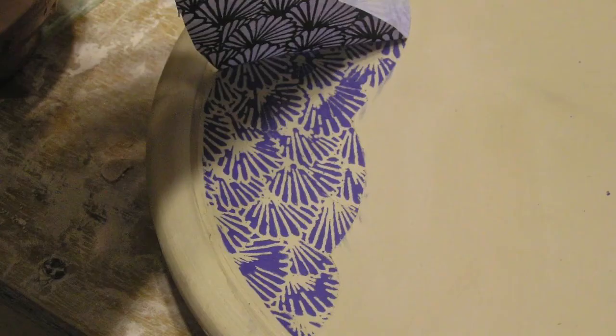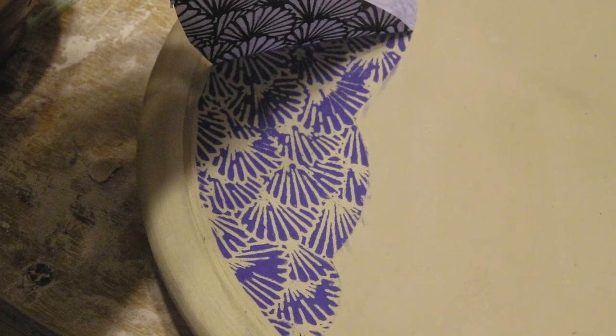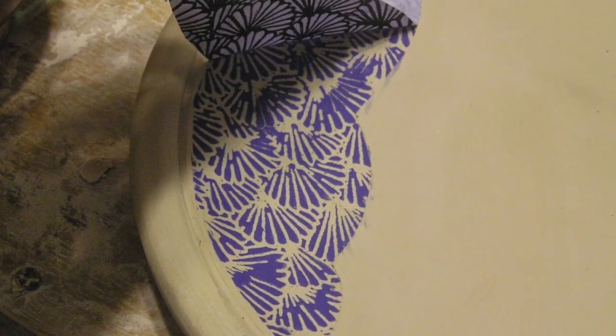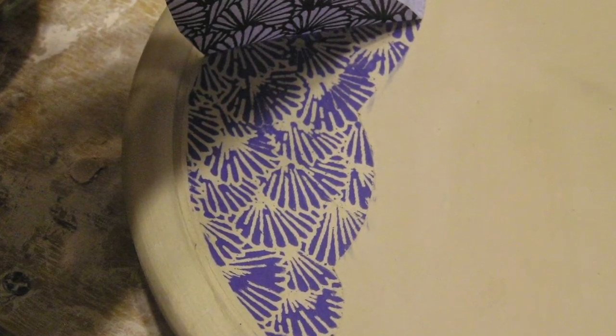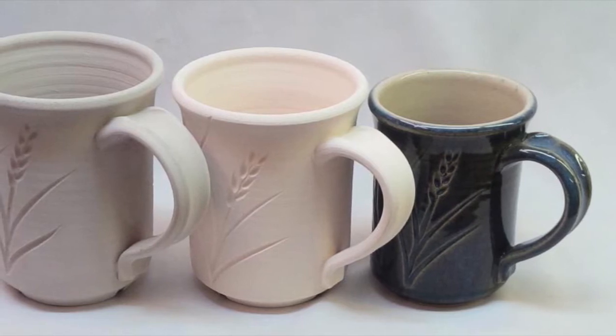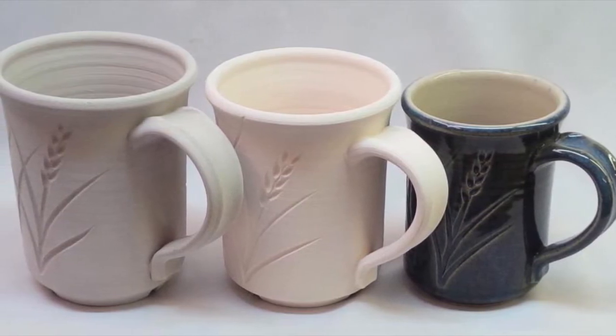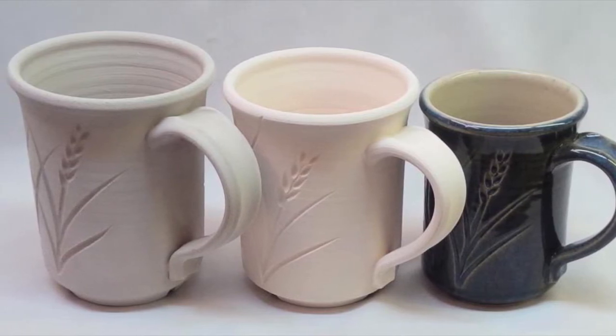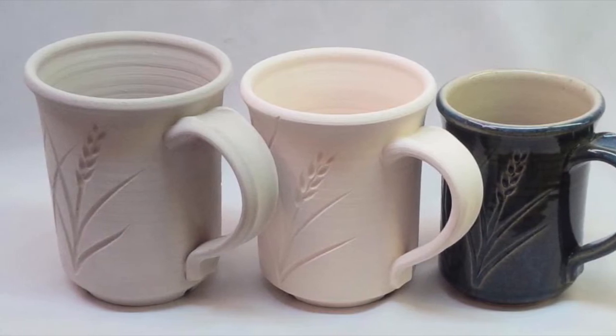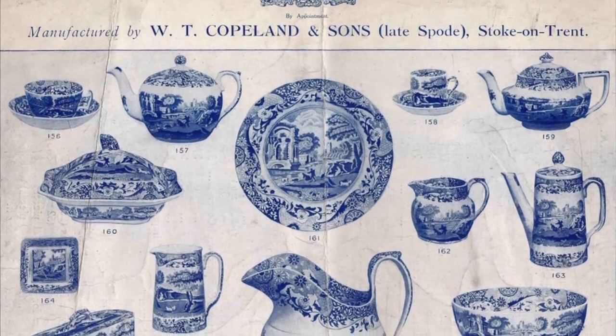So to mass-produce the images you see on these antique ceramics, many were made using a transfer printing technology that was actually started in the 1750s. Transfer printing involved the transferring of an engraved design on a copper plate using tissue paper or a glue bat onto a ceramic vessel. There are two primary types: one is when you print over the final glaze — which is when your piece has been fired twice and has a shiny sheen — or you apply it under the final glaze on the bisque-fired piece. A bisque firing is when you fire it once after drying your vessel when it's formed into its final shape, at a relatively low temperature to seal the clay, and then you can glaze it and fire it again to fuse the glaze onto your ceramic.